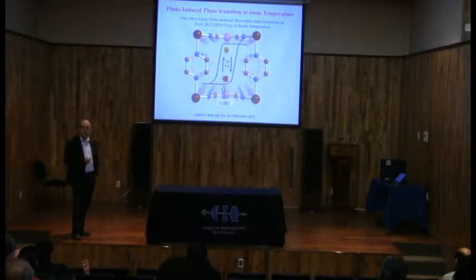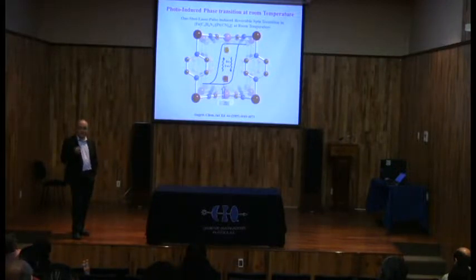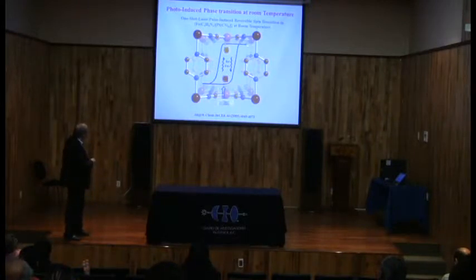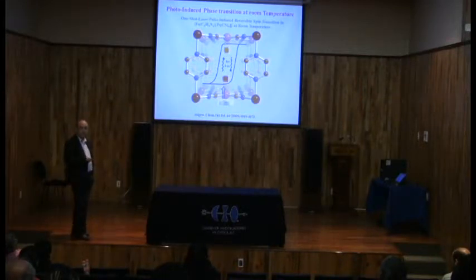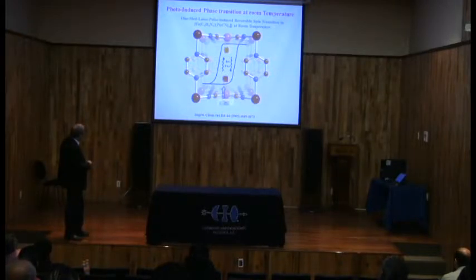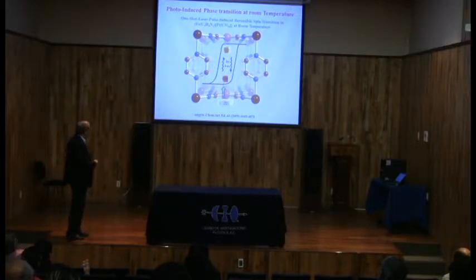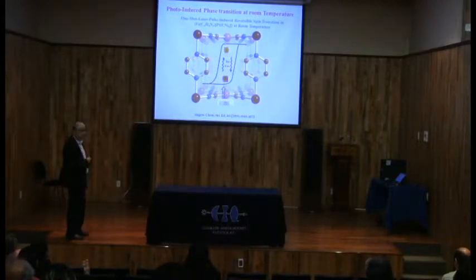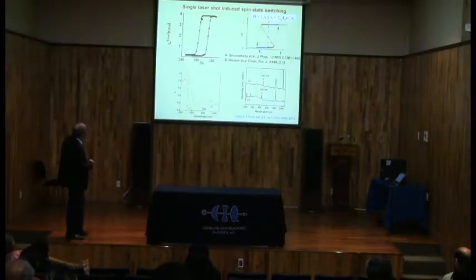Of course, when you have such a system, you need to see how we can address it, how we can write information, and how we can switch it quickly and easily. So we wanted to see if we can switch this system by light, for example with a pulsed laser beam at the nanosecond scale. I will show you that it is possible to switch this system reversibly between low spin and high spin by just 2 pulses of 8 nanoseconds, and the mechanism of this effect.